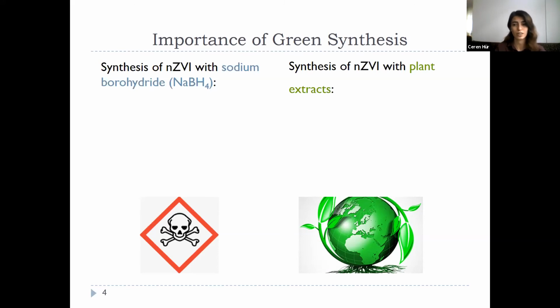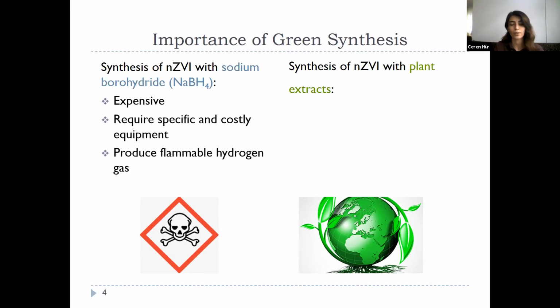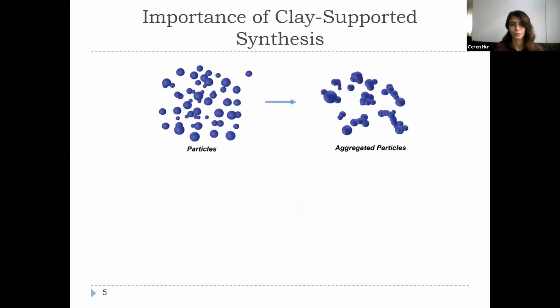it has some disadvantages such as being expensive, requiring specific and costly equipment, producing flammable hydrogen gas, and being a toxic chemical. Synthesis of NZVI with plant extracts has some advantages: eco-friendly, non-hazardous, low cost, and bio-waste. Importance of clay-supported synthesis. We don't want aggregation of nanoparticles because active surface area and efficiency are reduced.